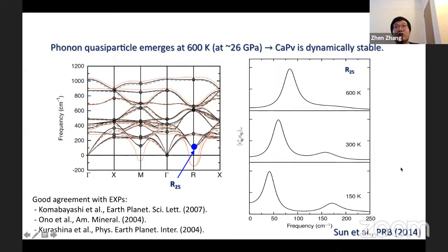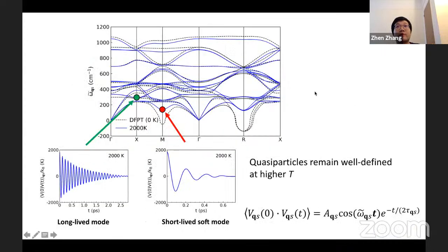So this non-cubic to cubic structure phase transition is a second-order phase transition, which happens below 600 Kelvin at this shown pressure. The transition temperatures agree well with several previous experiments. We further check the validity of the phonon quasi-particle up to 4,000 Kelvin. It is found that with increasing temperature, once the cubic phase is stabilized, the phonon quasi-particle remains well-defined before melting. Both the long-lived phonon quasi-particles and the short-lived ones are well-defined at high temperatures. Here I showcased some results at 2000 Kelvin.